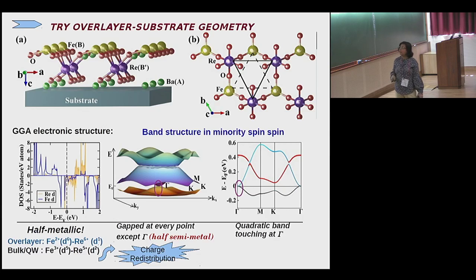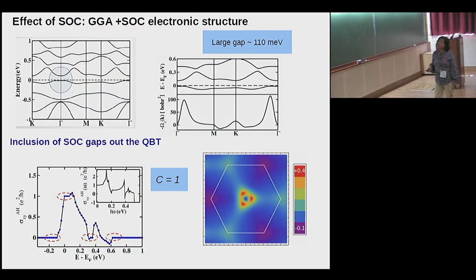This is still a half metal, but it is a half semi-metal because in the conducting spin channel, the bands are touching only at the gamma point, having a quadratic band touching at the gamma, being filled by only a single electron, which is in the d1 state, and that's your degenerate Eg pi level. Now you switch on the spin-orbit coupling, and that splits and opens the gap at the quadratic band touching.